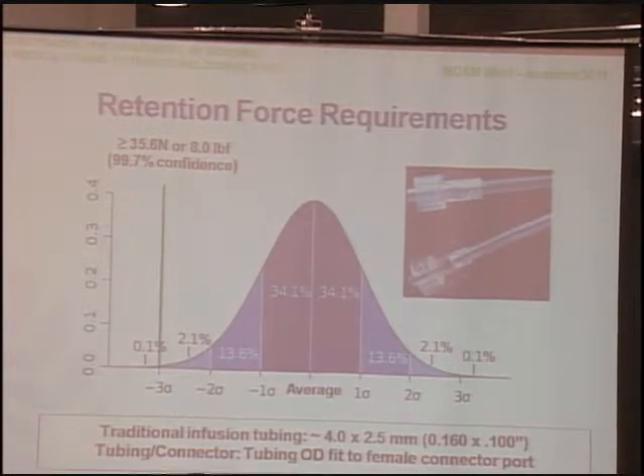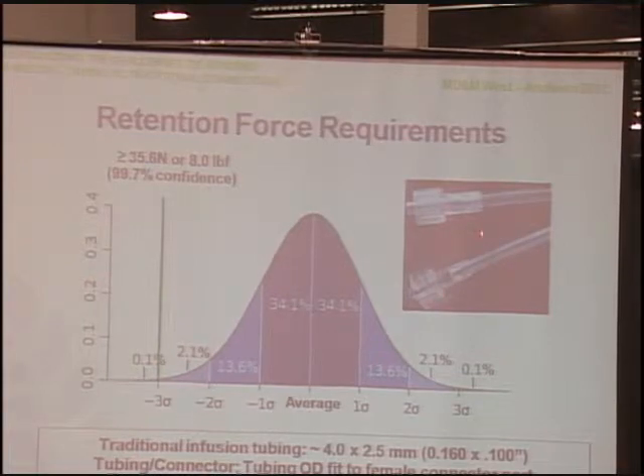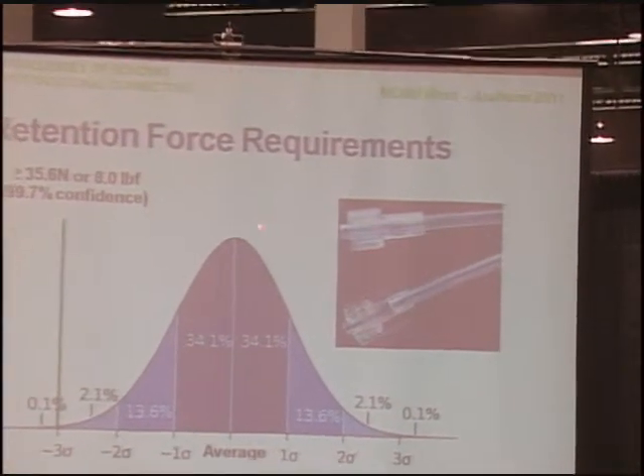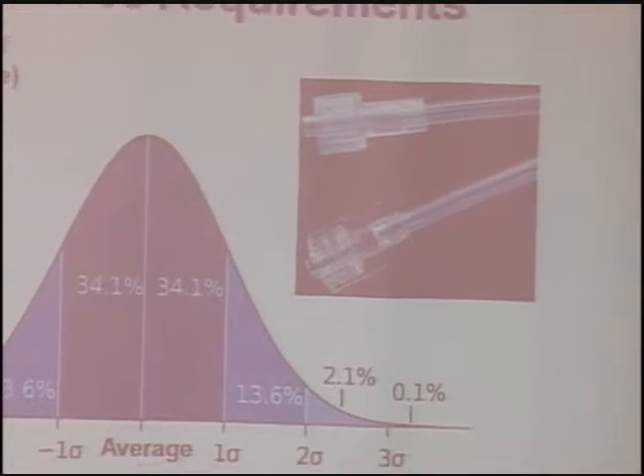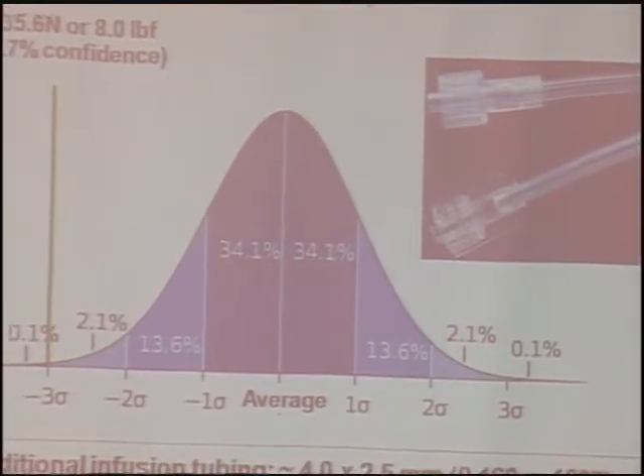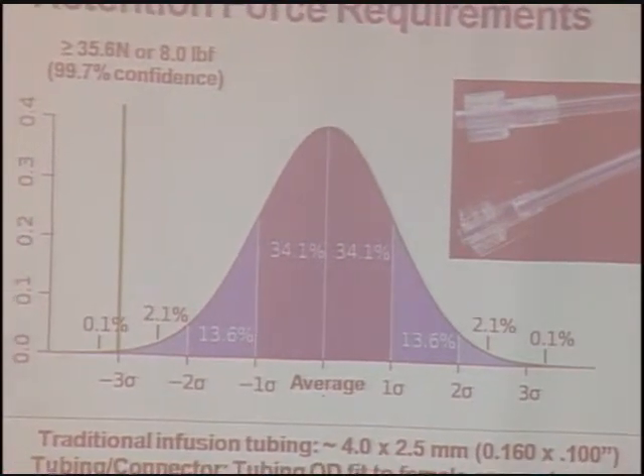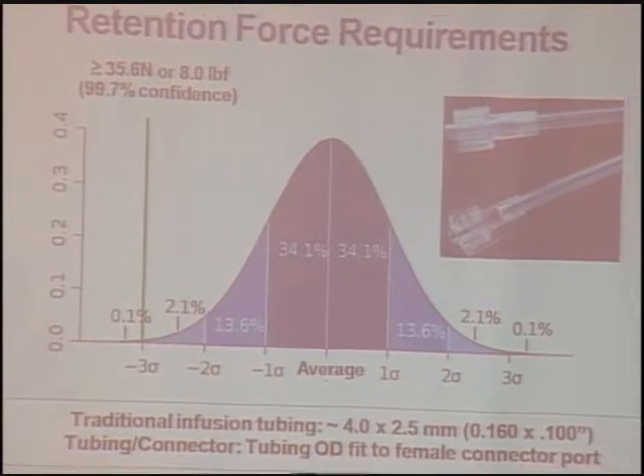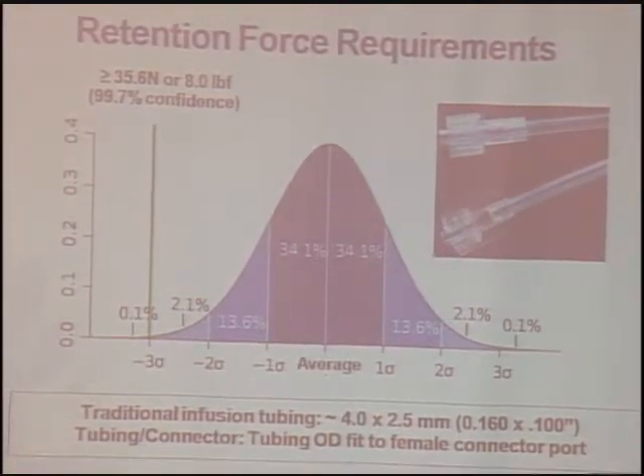Typical medical device, like a traditional infusion tubing, when it's connected to a female connector, if the size is 4 millimeter outer diameter and 2.5 millimeter ID, typically people want a retention force of 8 pounds or 35.6 Newton. But in many applications, people request not only the average to meet that requirement, but to meet it with significantly high confidence, 99.7%, which means the average minus 3 standard deviations has to be above their value.